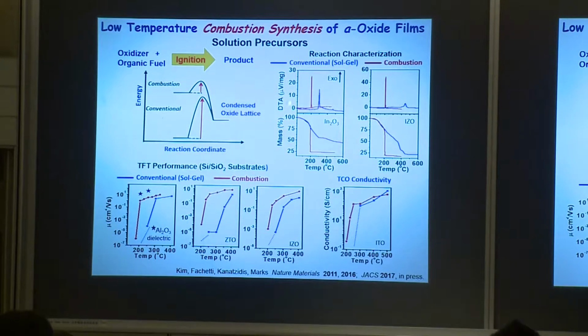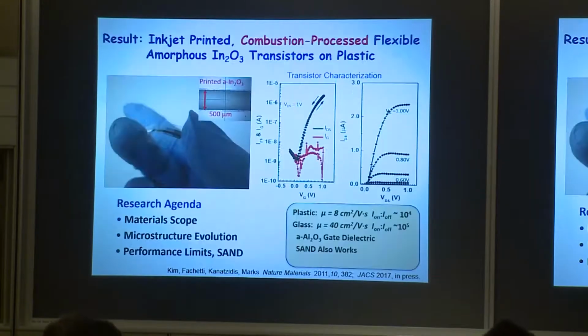And you can see this is differential thermal analysis, and we're comparing the combustion, we call this combustion synthesis, versus the sol-gel. So look how this is a very rapid exotherm at very low temperature, just enough to get it self-propagating. Here's the TGA. You can see very clean mass loss. And here are some crude initial transistors. I'll show you more in a minute. And it works quite well. But let's now put some finesse on.